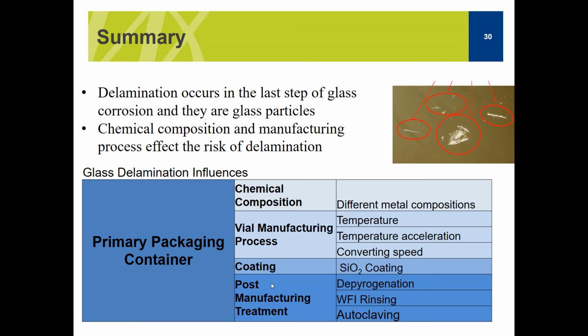And again, putting everything together, the different influencers of glass delamination are the chemical composition of the glass, the vial manufacturing processes, the coating, if we put an SiO2 coating, or siliconization, and the post-manufacturing treatment. And we did not really include siliconization in this module because you cannot sterilize siliconized vials, so they're not going to be part of our parenteral container, our parenteral packaging solution.